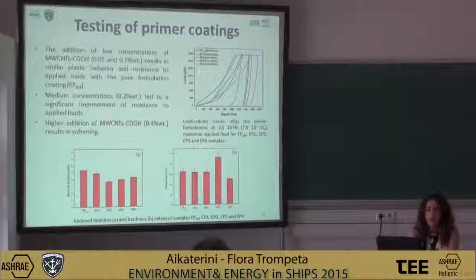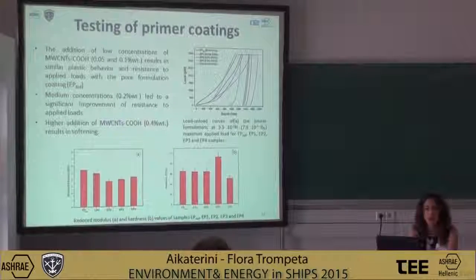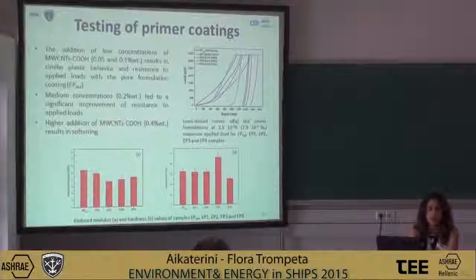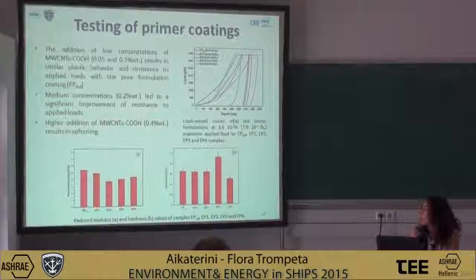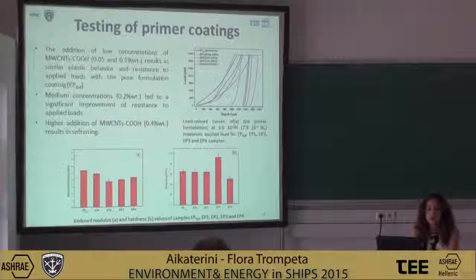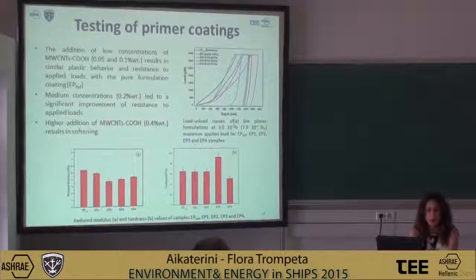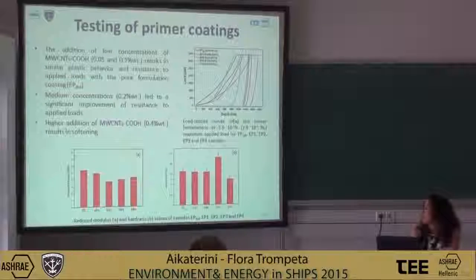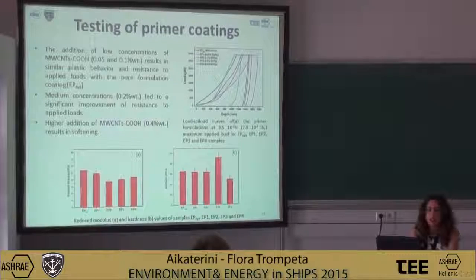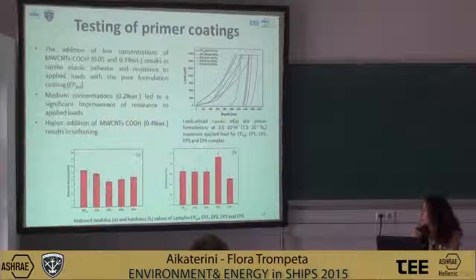The results of our study were that the addition of low concentrations of multi-wall CNTs with the carboxyl groups results in similar plastic behavior and resistance to the applied loads as the pure formulation coating. So we didn't observe any difference, as you can see from this chart. Medium concentrations led to a significant improvement of the resistance to applied loads. That means that we have a threshold concentration at 0.2 percent. Finally, the higher addition of multi-wall CNTs with the carboxyl groups resulted in softening of the material, as you can observe from the last column.